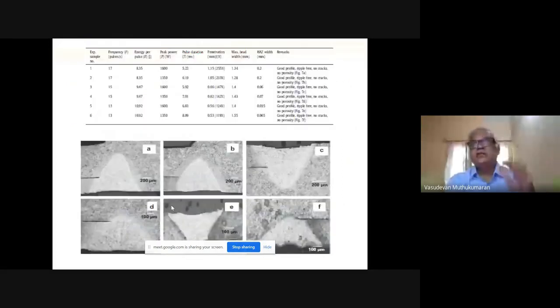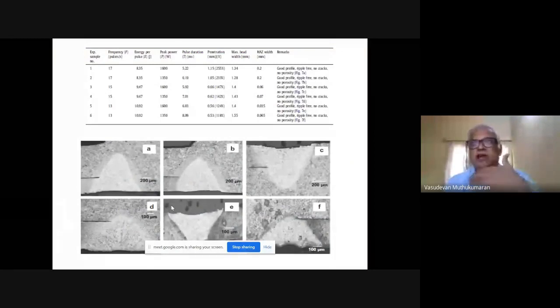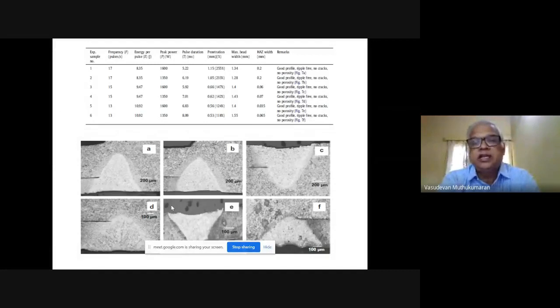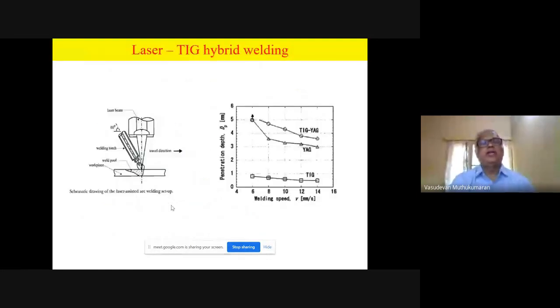Then with the same pulse laser welding system, because penetration is limited, as it's only a 500 watt system, we integrated a TIG torch. We specially designed fixtures to integrate the TIG torch with the laser gun, and we were successful. When you couple a TIG torch with the laser welding system, there is a significant improvement in depth of penetration at higher speed, and we can still avoid defects associated with the laser welding process, because we are combining two heat sources, laser and arc. Defects like porosity could be avoided, penetration could be improved, and defect-free joints could be fabricated.